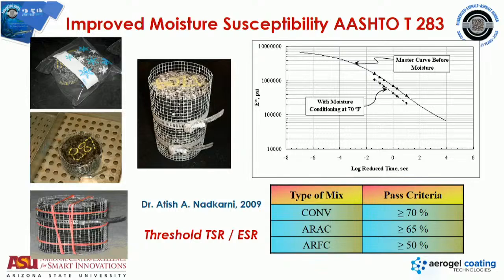The value is I have samples that I can test before and after, the same samples. I don't have to worry about segregation or aggregate distribution. Everything is exactly the same. You do it in the dry condition, and then you do it after the moisture damage.